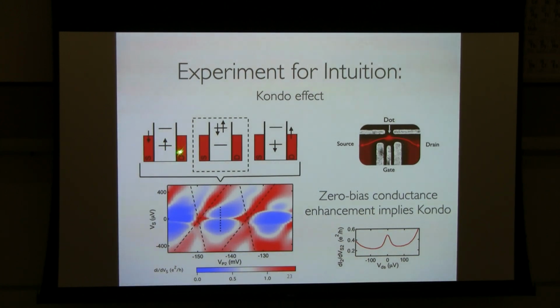And it comes about because even though we couldn't put one electron stably onto the system, it has, say, 21 electrons, it doesn't want 22, we could temporarily put an extra electron on and then tunnel off, and you can see that you have this process where the spin on the site flips, and this and higher order processes turn out to give rise to the Kondo effect and represent the screening of this local moment by the reservoir. And it shows up in this enhanced conductance, which is an enhanced density of states right near the Fermi level, right near the level to which electrons are filled. So this was sort of a dramatic qualitative demonstration, something that looked very different from what had been seen before.